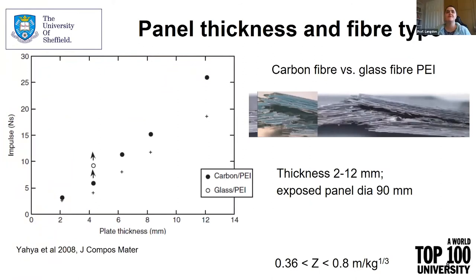This is some collaborative work with PhD students some years ago. Dr. Yahya is now an academic based in Malaysia. And in these experiments, we had a look at near field explosive detonations in glass fiber and carbon fiber laminates with a polyether imide resin system. The cross section on the right shows a typical failure. So you're looking at the cross section, you can see cracking, fiber fracture through most of the layers, if not all of them, and some interlayer delamination.